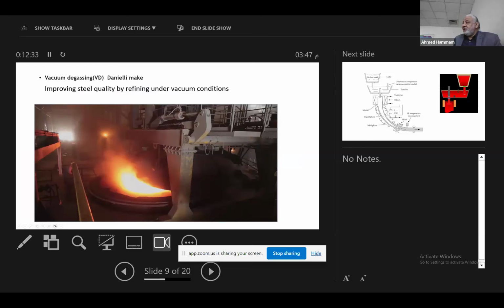For the vacuum degassing, as you see from the picture here, it is the ladle after the LRF. Then the cover should be put above this to be isolated from the atmosphere, and then the cycle starts for creating the vacuum inside this ladle by mechanical pumps in order to reach a pressure around 1.3 millibar. To reach this stage of 1.3 millibar, it takes around 6 to 7 minutes. After that, we keep the ladle under vacuum for around 20 minutes.